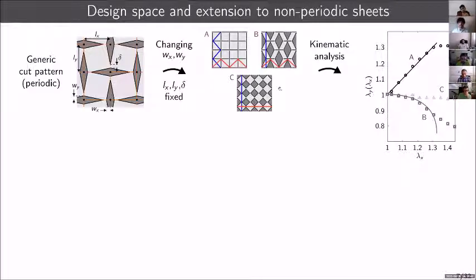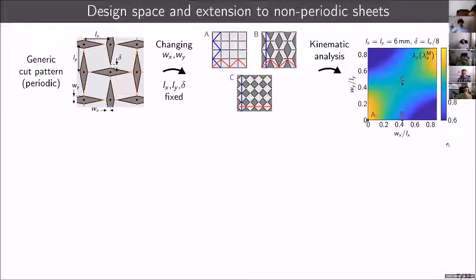On the other hand, the geometry in C. If we look at this pattern, you can see that these lines connecting the joints are already straight before pulling, and therefore there is really no mechanism. And for that reason, this geometry in C is much stiffer than the other two. So what we can do is to actually create some design maps where, based on a certain stretch or certain mechanical behavior that we desire, we can backtrack what is the cut pattern needed in order to obtain it.